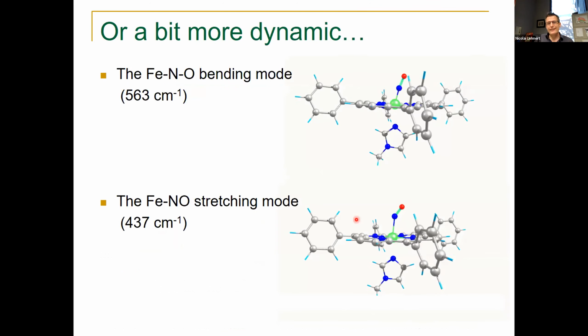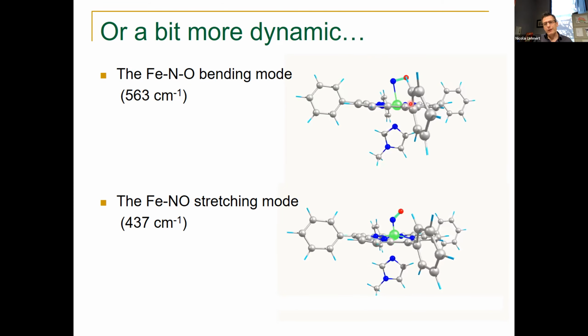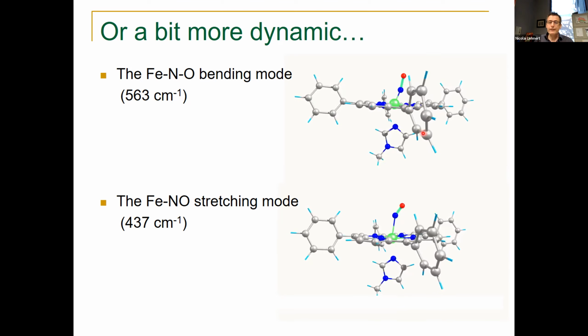You can also look at this with the nice animation pictures. So here is the stretching mode. Iron essentially moves straight out of the plane of the heme. And here is the bending mode where the iron kind of moves on this diagonal. It's a dominant bending mode, but it has some stretching character as well. And being able to simulate the polarized intensities really allows us to end up with a simulation where we have high confidence that we really figured this out.